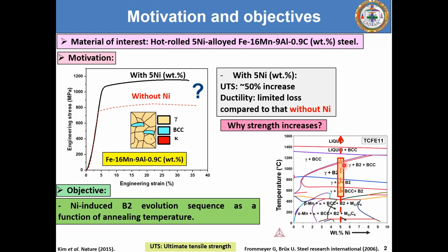Whereas at a narrow phase field around 1100 degrees, the gamma plus BCC plus B2 phases are thermodynamically predicted to be stable. And then at a temperature of nearly around 1200 degrees, only the two phases, namely the gamma plus BCC phases, are thermodynamically predicted to be stable for the 5-8% nickel addition. So with this, we have further studied the influence of the nickel-induced phase evolution on the mechanical response.